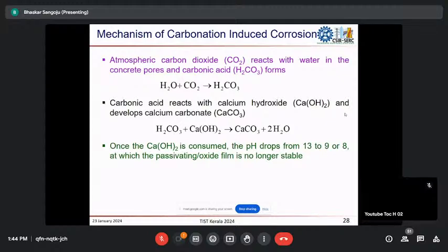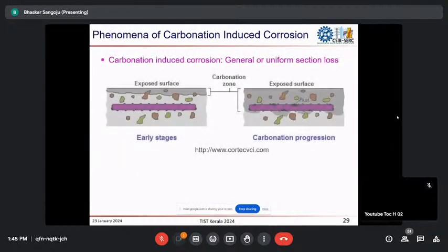So when it drops down to 10 and below, then the passive layer, what I told earlier, will become destabilized, depassivated, and will no more be available for protection of the rebar. So this is the phenomenon of carbonation induced corrosion. That means when the concrete is exposed to an industrial environment or carbon dioxide exposure conditions, the CO2 tries to enter inside the concrete and reacts with it, the pH drops down, and you can see a more uniform type of rebar corrosion.